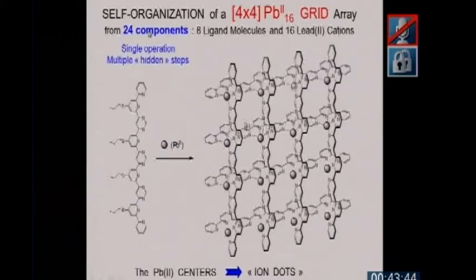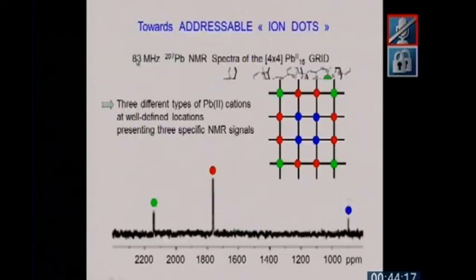but also, if you look at the lead, what can you see? There are 4 identical leads in the corners, they're identical. There are 8 identical leads in the edges, and there are 4 identical leads in the middle. Now, you know perhaps that the nucleus of lead has a spin 1/2, like the proton has a spin 1/2, and therefore you can look at it by lead NMR. At 83 megahertz, the NMR of lead 207, this is again the disposition of the different leads, and you can see you have green 4, red 8, and blue 4, 1, 2, 1. This is the NMR spectrum.